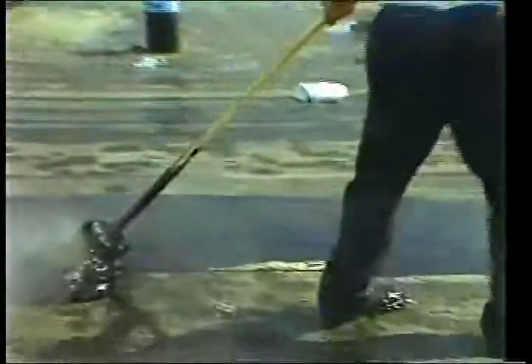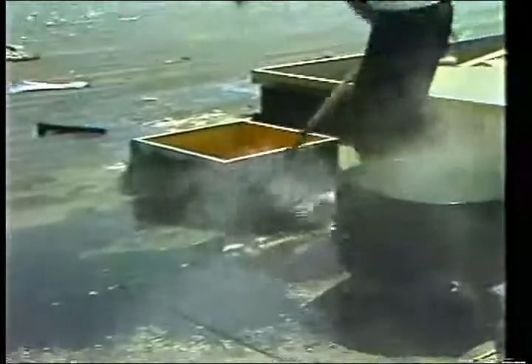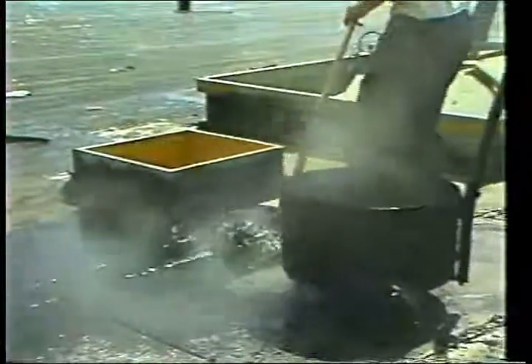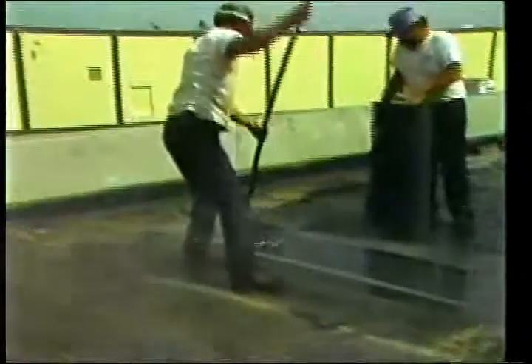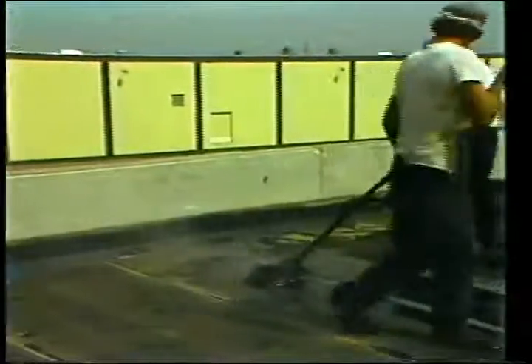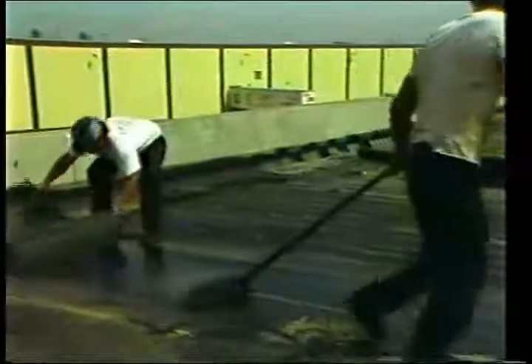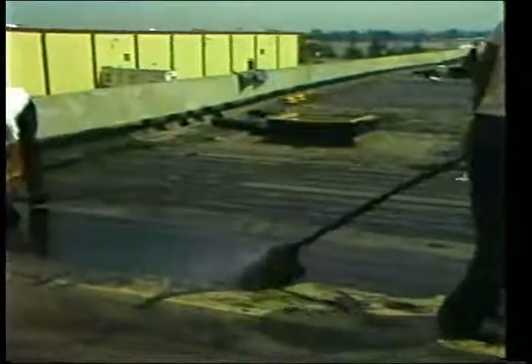With fiberglass, asphalt coverage is increased and improved, and an even distribution of asphalt with no voids is possible. Fiberglass mops glide across roof surfaces, while cotton mops tend to drag. In this comparison of fiberglass and cotton mops, you can see that the flow of asphalt from the cotton mop is reduced, and the roofer has difficulty getting good coverage, even though the mop is still saturated with asphalt. Because the flow of asphalt is slowed, the tail of the mop cools and drags across the roof.